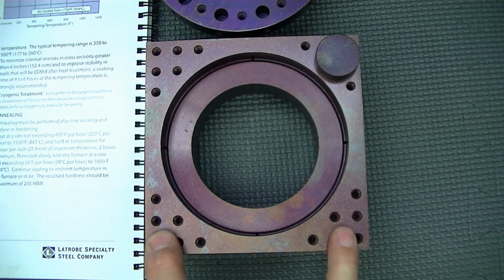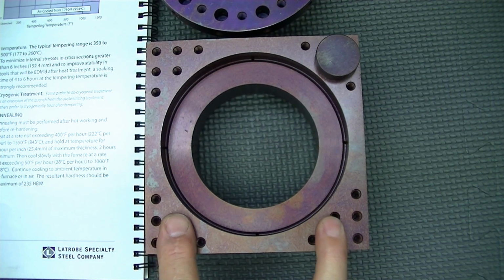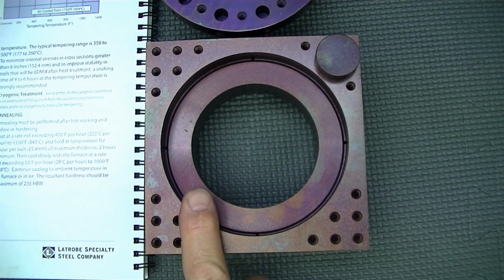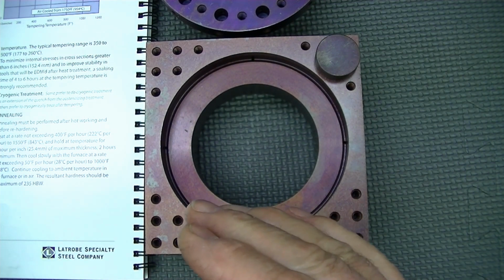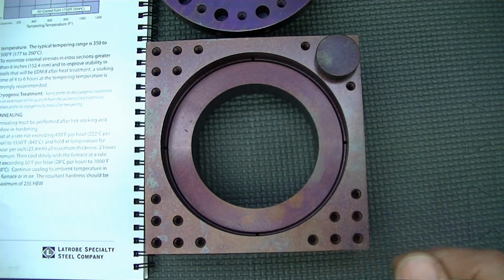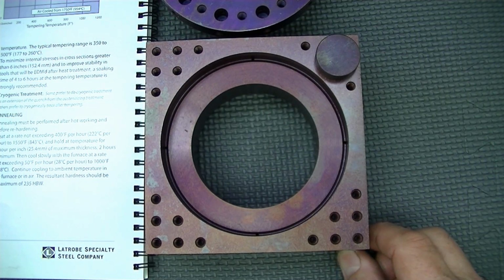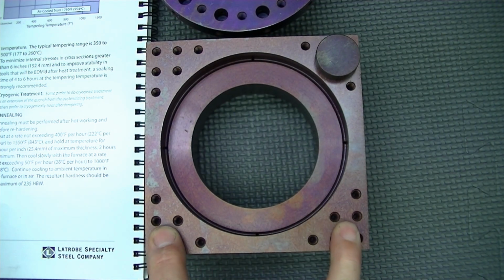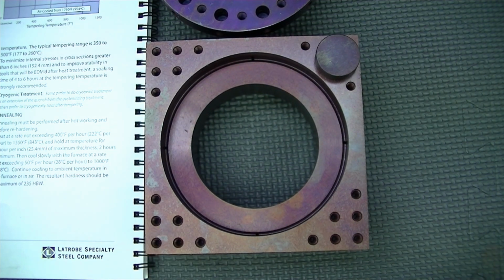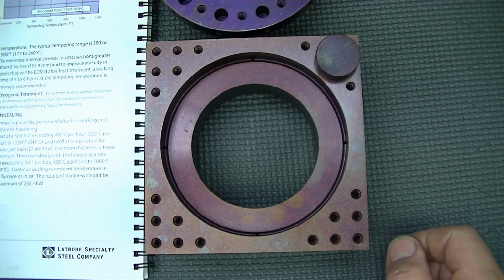What that means is vacuum hardening is done in a vacuum chamber. It's taken up to temperature through the recommended cycles for the material, how long you take it up to what temperature, let it soak, and then carry up to the actual heat treat temperature, and then the quench. Well, in the vacuum furnace, the quench is actually done with a high pressure gas that's recirculated through the heat treat oven, and has a heat exchanger on the outside to rapidly remove the heat that it's absorbing out of the parts, take it out of the gas, and when it goes back in again, it's chilled.